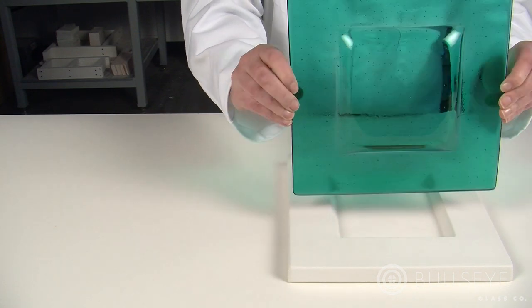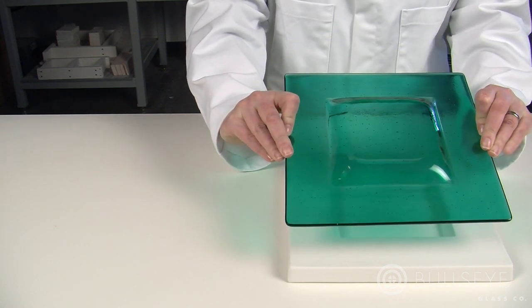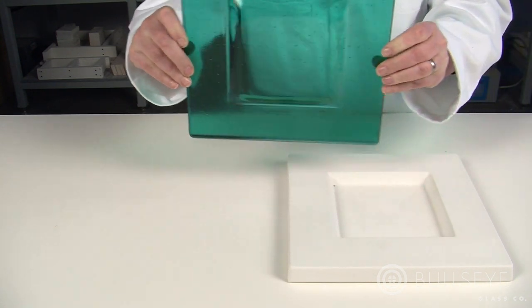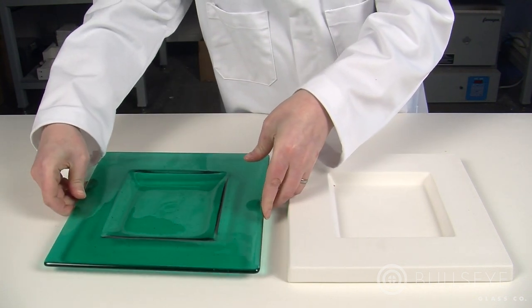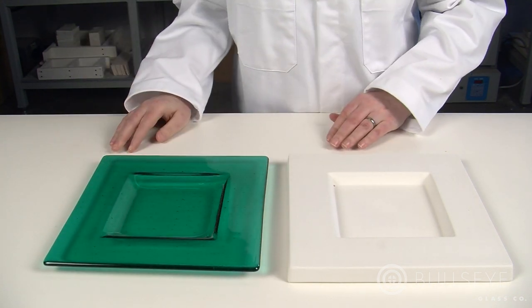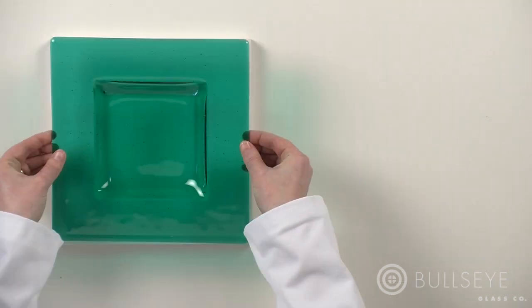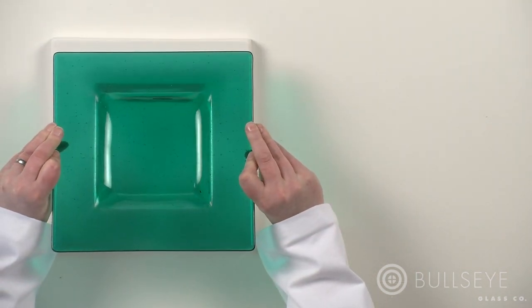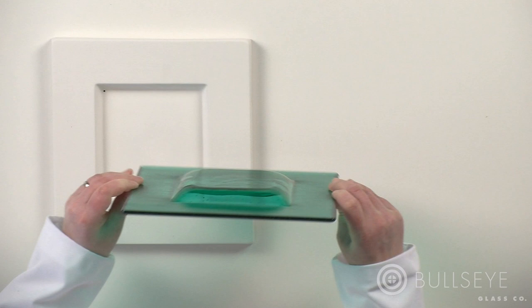Greater heat work was required for the glass to take the shape of a square platter mold with a recessed area approximately 5 by 5 by 1.5 inches deep. The process temperature was 1250 degrees with an hour and 15 minute hold.